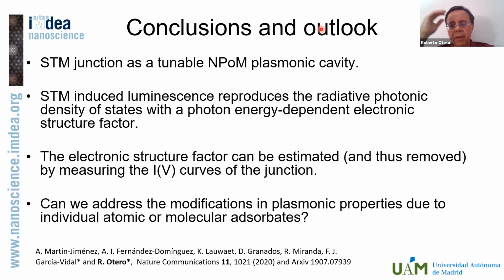If you have a look at the literature, you're going to find people who claim that the intensity increases or that the plasmonic intensity decreases or that it red shifts or that it blue shifts. It's not very clear what they have truly measured. I would say that after our work, I have some doubts as to whether they are not just measuring electronic properties and not truly optical properties.